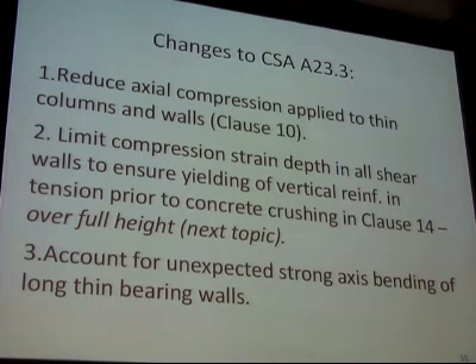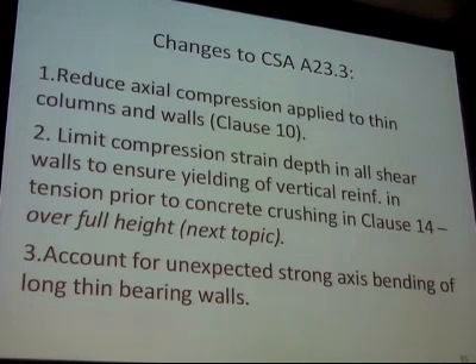The other thing, we've got to be really careful of limiting the compression strain. I'm actually not a big fan of confinement. A lot of people think you got to confine everything. I think you just got to avoid the large compression strains, and then you don't have to confine it. If you're going to have high compression strains, you've got to confine. If you keep the compression strains low, then you don't actually need to confine.